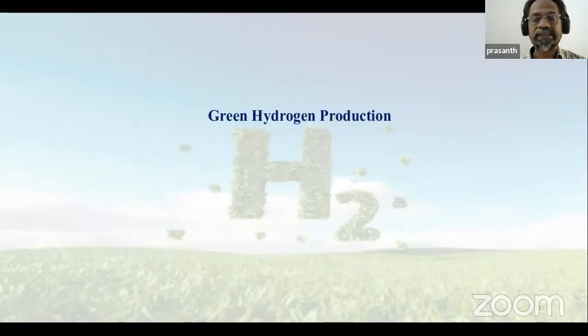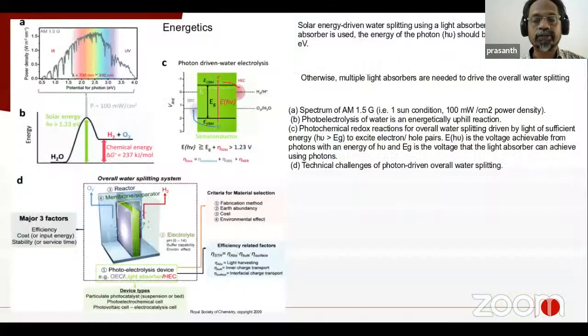And so the next application is hydrogen production. Hydrogen production is done simply by water splitting, because hydrogen is the cleanest energy possible in the environment. But the current commercial hydrogen production methods are not completely green pathways; emission is happening in that. If you use solar energy for water splitting, then you could reduce the carbon footprint of hydrogen production considerably. But how to give the required energy, because there is an energetics working in the splitting of water. You need 1.23 eV energy to split the water.